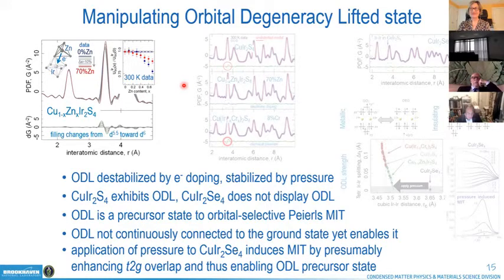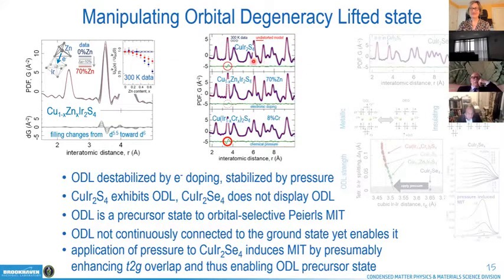Fine. So we have also done cubic model assessments of our data. So here is our effect in the original sulfur system. And we see that as we dope sufficient amount of zinc, meaning as we change filling from 5.5 towards 6, we're removing the effect in zinc substituted system. On the other hand, if you put chromium on iridium site, and chromium is appreciably smaller, and it actually contracts the lattice, what you do see is enhancement of this effect. So pressure presumably stabilizes this effect. So in principle, you have knobs to manipulate this state pretty nicely.